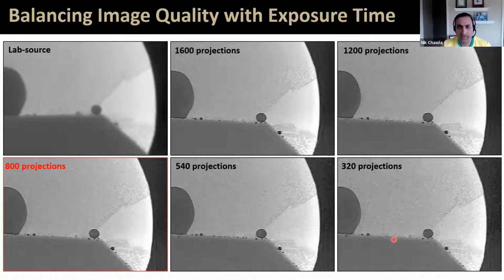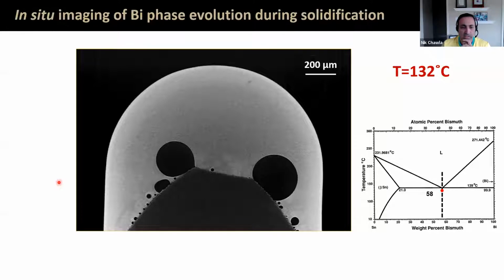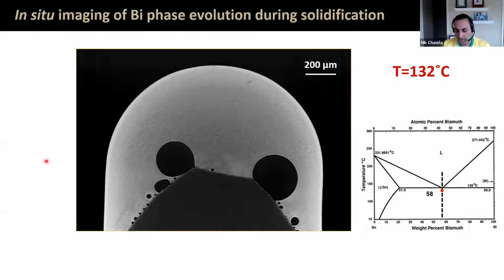And then we did a comparison of the number of projections. On the top left is the same sample, a section from the lab source. And on the bottom right, you have the lowest number of projections, so that would be the fastest possible scan. And we zeroed in on something like 800 projections where we could get a nice balance of efficiency, fast scanning, but still fairly good quality imaging. Okay, so here, let me show you just a 2-dimensional image from a 3-dimensional scan during the solidification process.